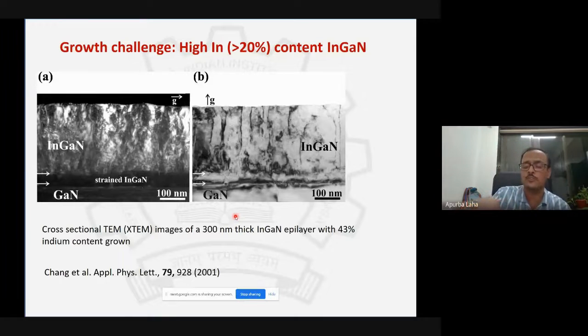So that's the beauty of these ternary systems. If you have to achieve green light, you need an indium content of the order of 20% in order to get emissions of, let's say, 500 or 530 nanometer. That is again more challenging, because indium and gallium have very different thermodynamic properties, as is true for aluminum and gallium as well. So these are basically the challenges the grower faces to come up with a good quality crystal layer.